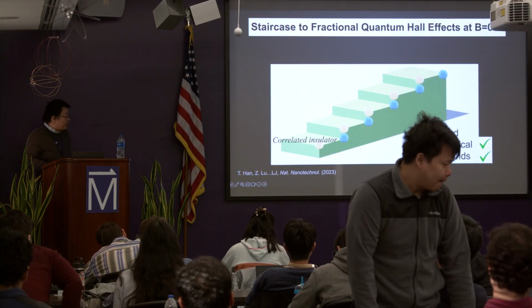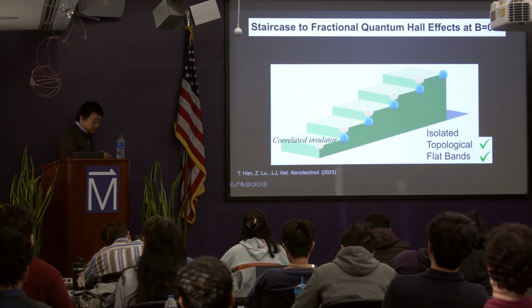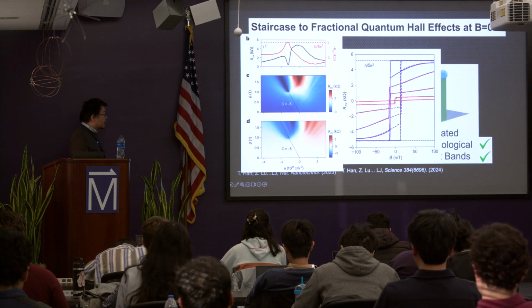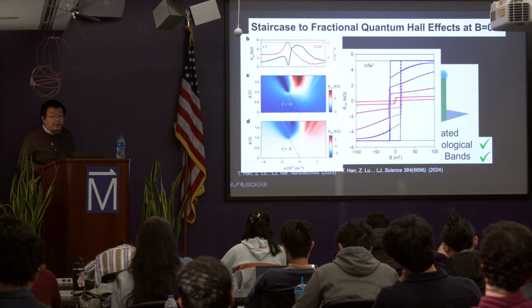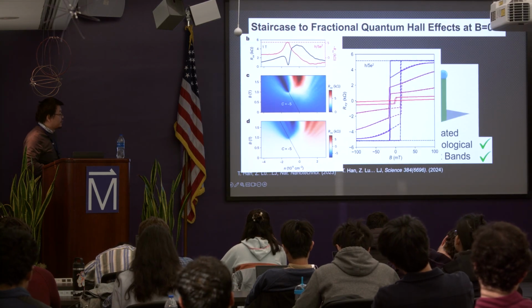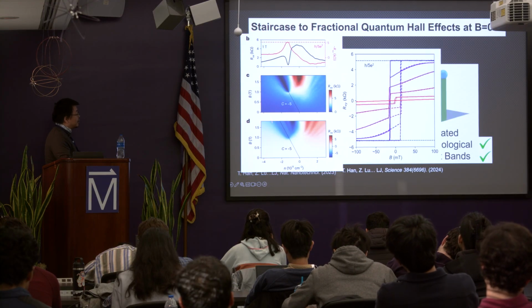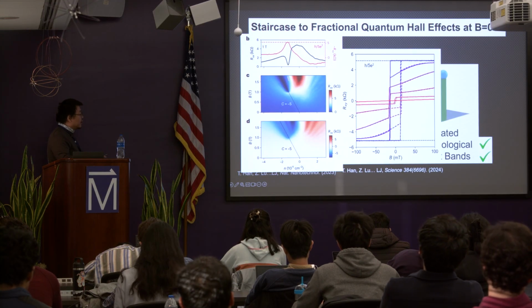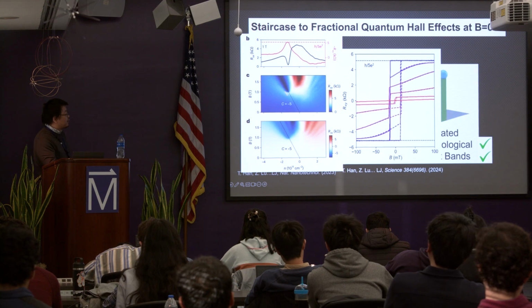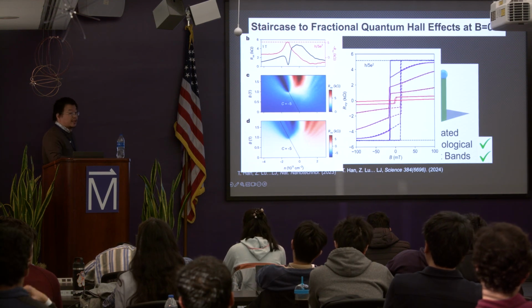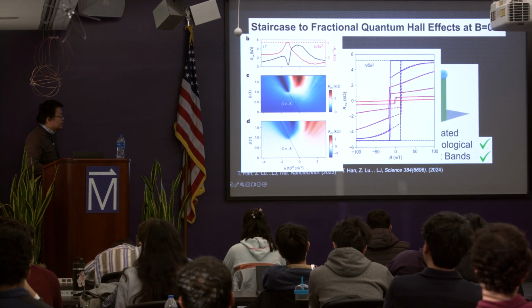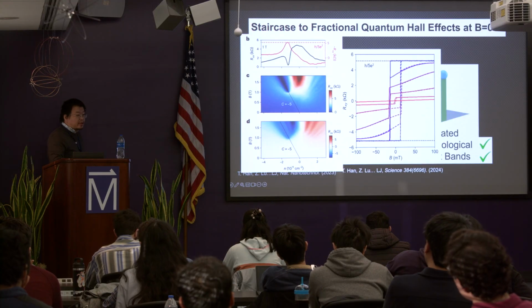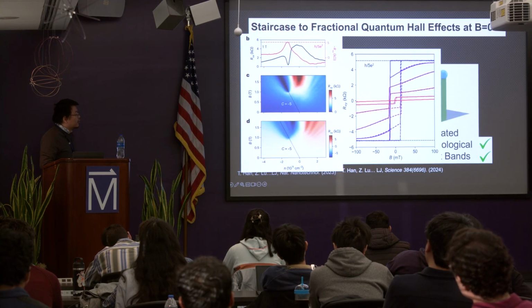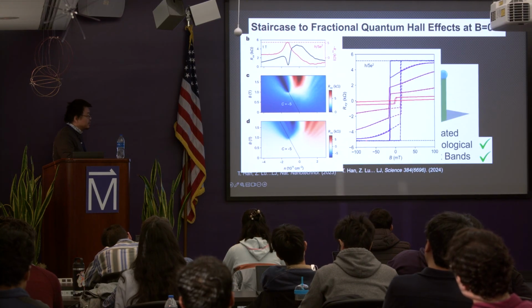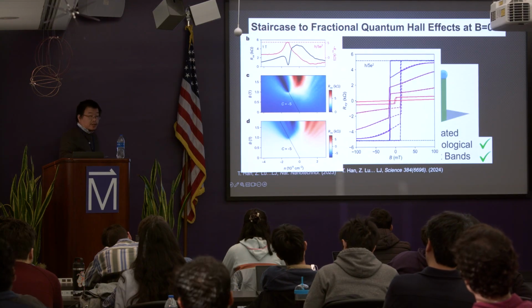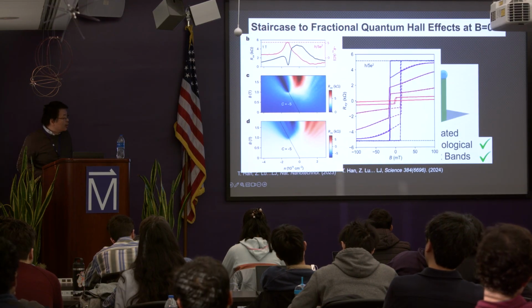So we're kind of crossing the second one as well, and there's also a lot of experimental evidence it is indeed topologically non-trivial. For example, this is a pentalayer graphene device, and it shows a C equals 5 Chern insulator at about 1 Tesla. And it can also be stabilized by approximating spin-orbit coupling, and it can bring this Chern insulator down to zero magnetic field, which is the integer quantum anomalous Hall effect.